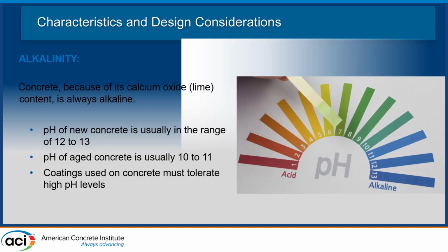And then the other thing is new concrete has a very high pH. As concrete ages and is exposed to the atmosphere, carbonic acid or other contaminants will lower the pH. And low pH is not our friend. We want a good high pH of 10 to 11 or higher before we apply our coatings. If you have a low pH below 9 or so, you have degrading concrete. It may be a very slow process, but it is degrading. And if you coat over that, the concrete will continue to degrade because you still have low pH.